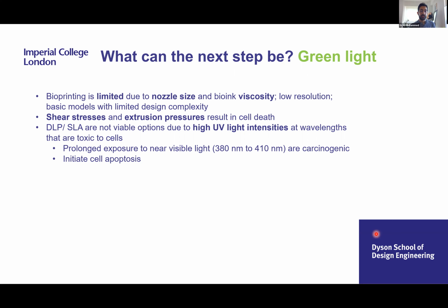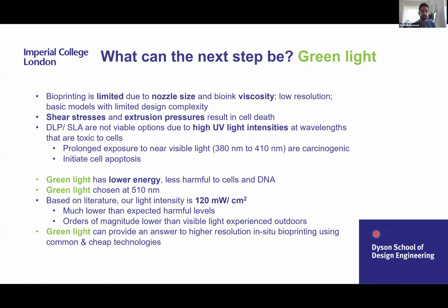However, while cells withstand intensities of above around 1 kilowatt per centimeter squared at 614 nanometers for several minutes, the maximum dose at 405 is only 100 to 200 milliwatts per centimeter squared. So you are really limited by how long you can expose them. In contrast, green light has a lower energy and is less harmful to cells and DNA. So green light, which we chose at 510 nm, is a very viable option for bioprinting using light.